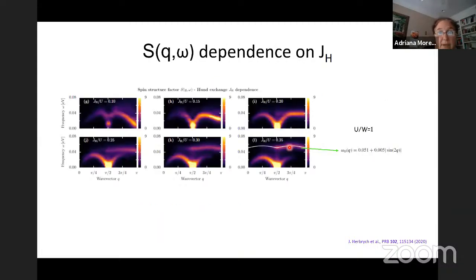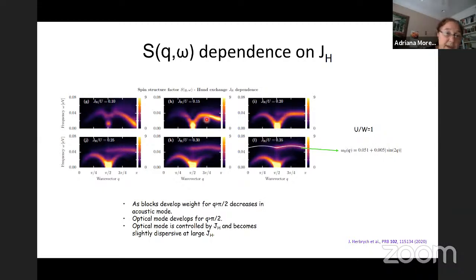So now let's see what happens as a function of J. It's kind of similar. We work now at U over W equal to 1. And again, we see that eventually when we get to J, so that the blocks start stabilizing, we get a lot of spectral weight at pi over 2. It becomes more intense. Eventually the blocks form and we get the optical mode. And as J Hund continues to increase, now the optical mode gets separated and increases more with J.